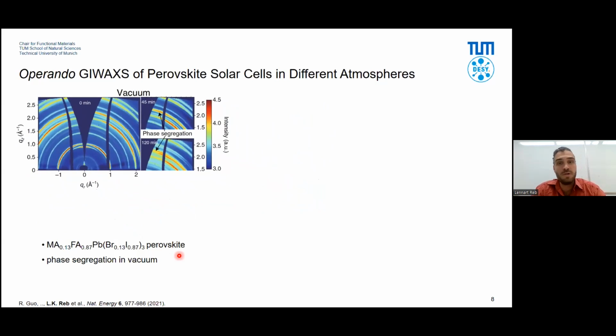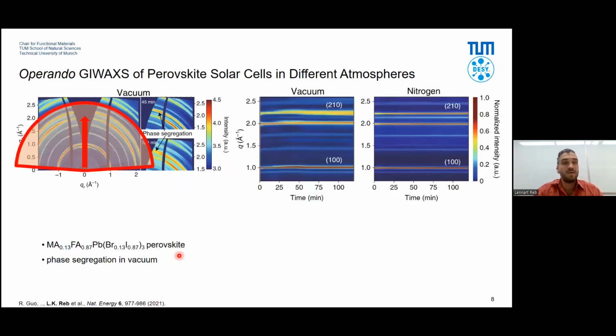So what we can do is we integrate the signal radially and fold it to a line cut. And then we can plot this line cut over time. So we have multiple vertical line cuts here, and we can see how things change with time. For the sample in vacuum, you can see that actually, yes, here's something changing, here's something weird, while in nitrogen atmosphere, it seems to be completely stable.